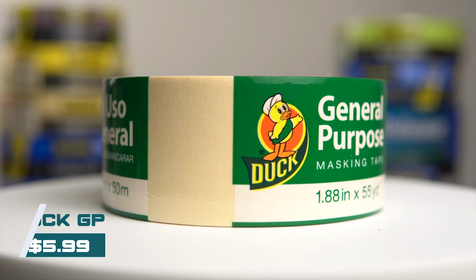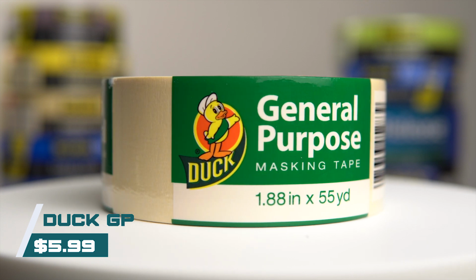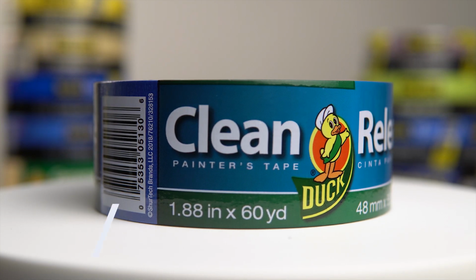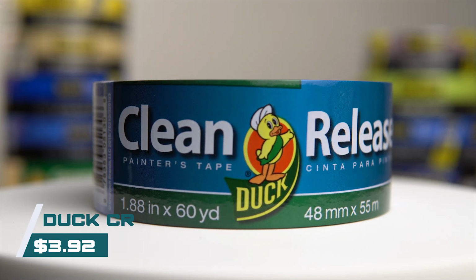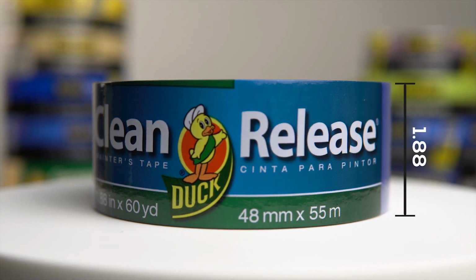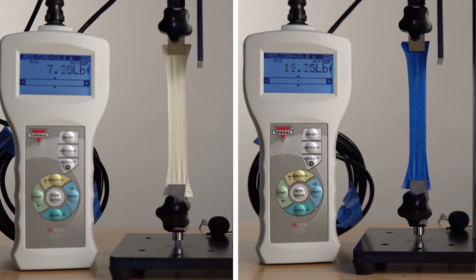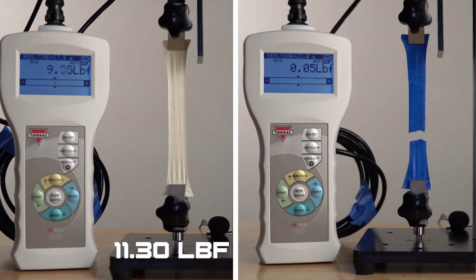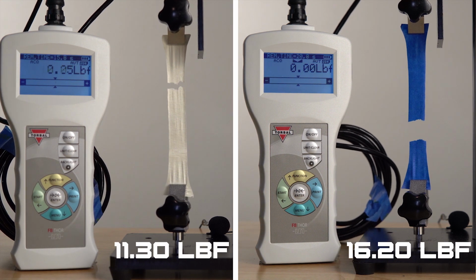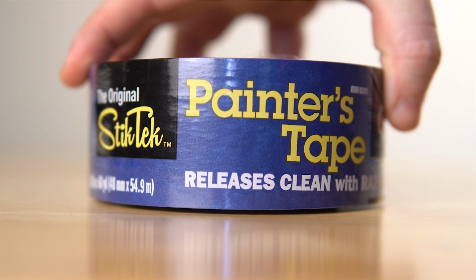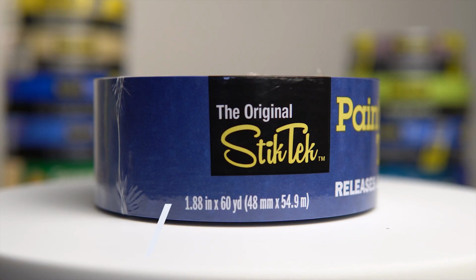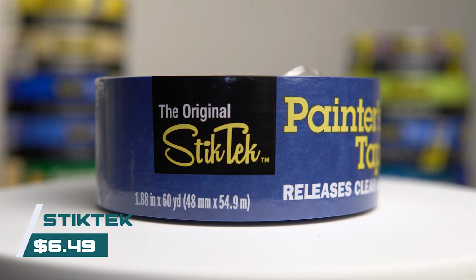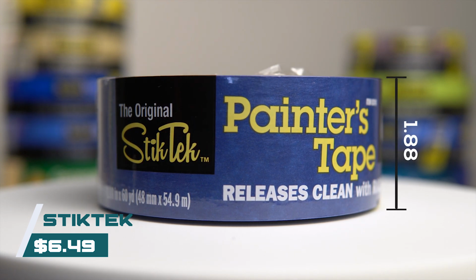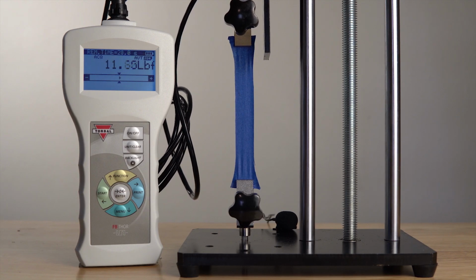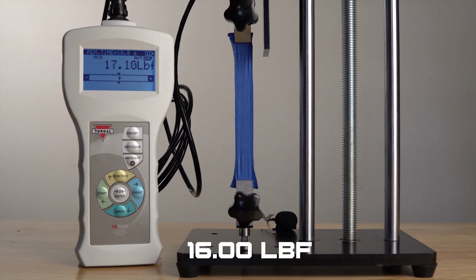Next up, we have the Duck Brand General Purpose with a price of $5.99 and Duck Brand Clean Release with a price of $3.92, both for the 1.88 inch roll. They had an average maximum tensile strength of 11.30 and 16.20 pounds of force respectively. Finally, we have the Harbor Freight Stick Tech Painter's Tape. It has a very affordable price of $6.49 for the 1.88 inch roll. Stick Tech comes in with a very high tensile strength of 16 pounds of force.